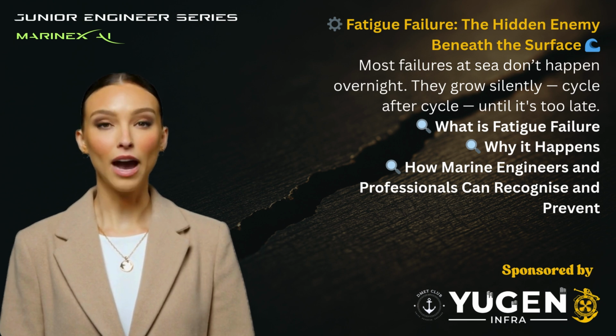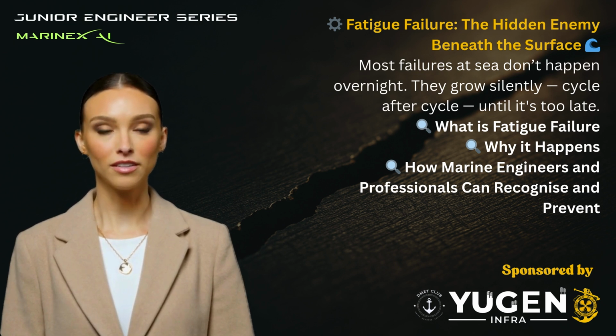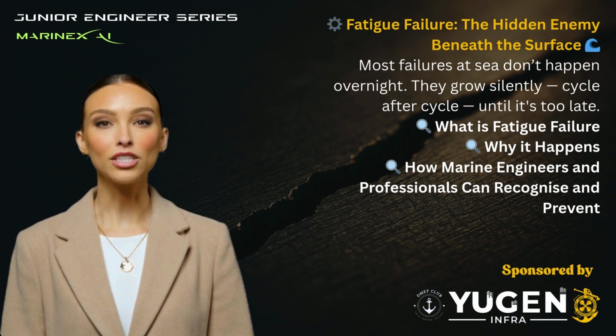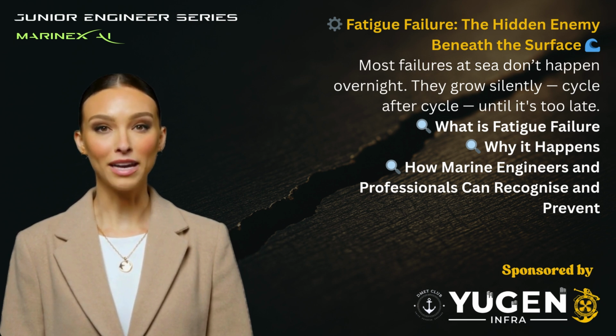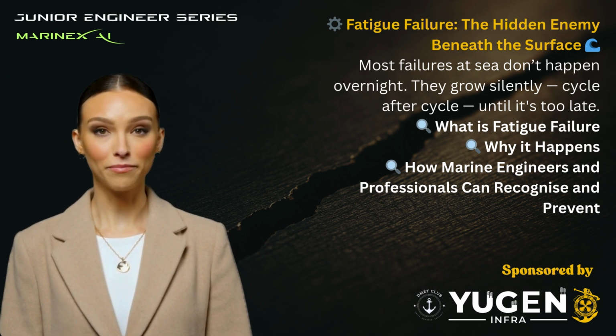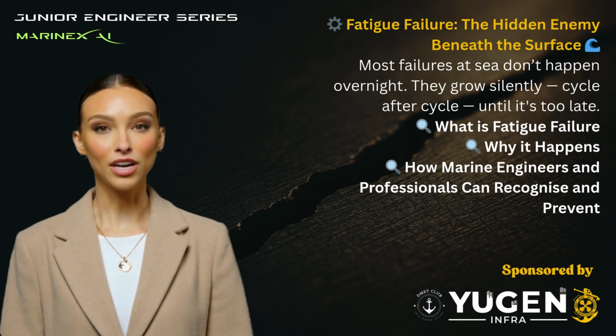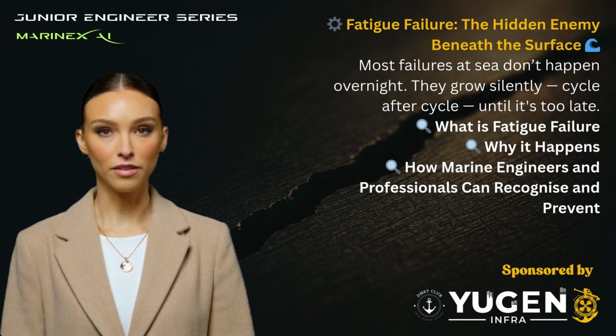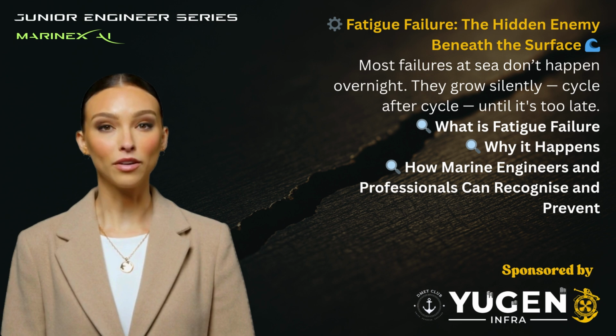Recognition of fatigue failure. Identifying fatigue failure involves examining the fracture surface. Smooth area: the region where the crack initiated and propagated slowly appears smooth and may show beach marks. Rough area: the final fracture area, where rapid failure occurred, appears rougher and may exhibit a cup and cone morphology in ductile materials. The presence of both smooth and rough regions on the fracture surface is indicative of fatigue failure.